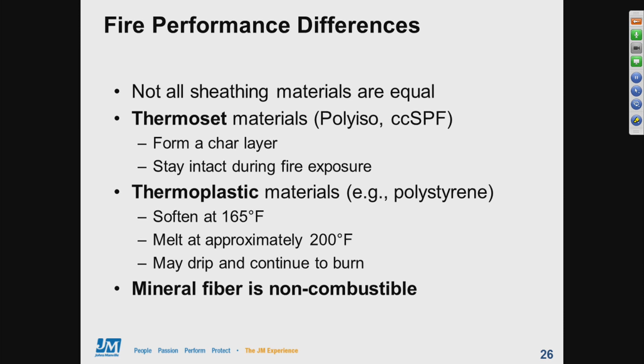So we've touched on this before, but it really does bear repeating that sheathing materials perform differently when exposed to fire. Thermoset plastics, again, such as polyiso and closed-cell spray polyurethane foams, char and tend to stay intact during fire exposure. Thermoplastic foams, such as polystyrenes, can soften and melt and can even drip burning liquids in a fire situation. Finally, mineral fiber, though, is non-combustible, and so it really provides the best fire performance of all CI materials.